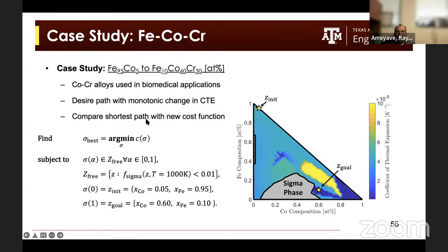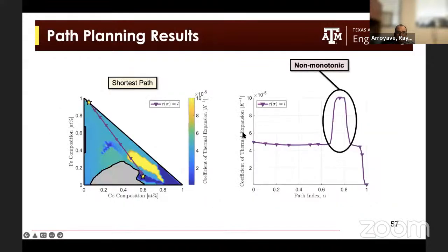Okay, so this is an example. We looked at the iron, cobalt, chromium system, and we tried to map a path that connected two different compositions. We formulated an optimization problem where we tried to minimize the length of this trajectory while ensuring that we didn't have a particular phase, that we avoid obstacles, and at the same time we tried to make sure that the path was monotonic in thermal expansion coefficient.